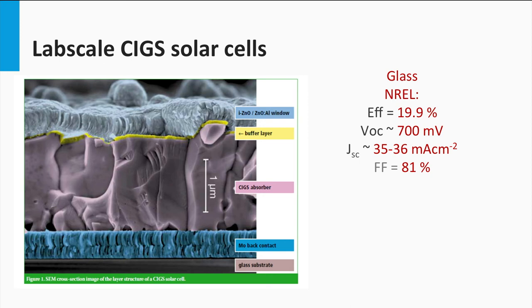Typical open circuit voltages are close to 700 mV, the fill factor of 81%, and short circuit current density between 35 and 36 mA per square cm have been achieved. The world record on flexible substrate has been obtained at the Swiss Federal Laboratories of Materials Science and Technology. The CIGS cell on a flexible polymer foil resulted in an impressive conversion efficiency of 20.4%.